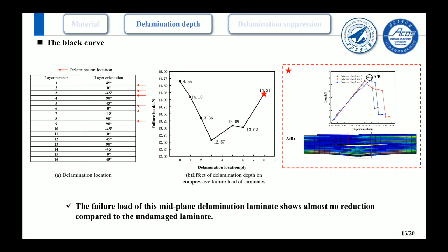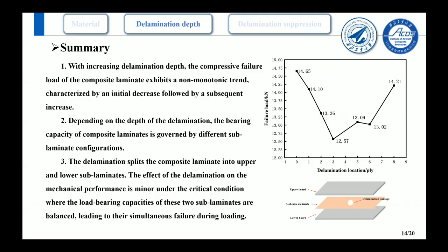Finally, attention is turned to the black curve in the figure, which represents the case where the delamination is positioned at the midline of the laminate. Due to the symmetric layout, the upper and lower sublaminates are nearly identical. They consequently underwent simultaneous wrinkling, leading to an instantaneous load drop. Notably, the failure load of this midplane delamination laminate shows almost no reduction compared to the undamaged laminates.